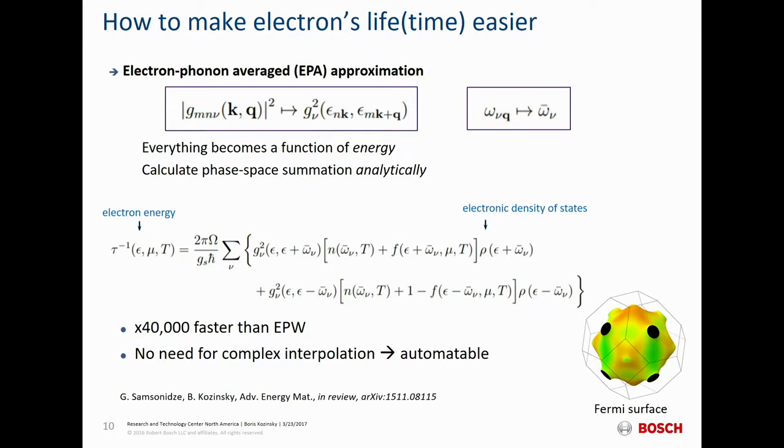And the approach we took was to try to move the integration, which is complicated in K and Q space, in momentum space, and move it into the energy domain. So replace some of these KQ-dependent quantities, like the electron-phonon coupling matrix, with one that depends only on the energy. So essentially remove the directionality dependence from the integral, and also replace the phonon dispersions by a simplified model where we have optical bands with some frequencies that don't depend on the momentum vector, which is a good approximation at higher temperatures where your optical phonons really dominate the scattering.